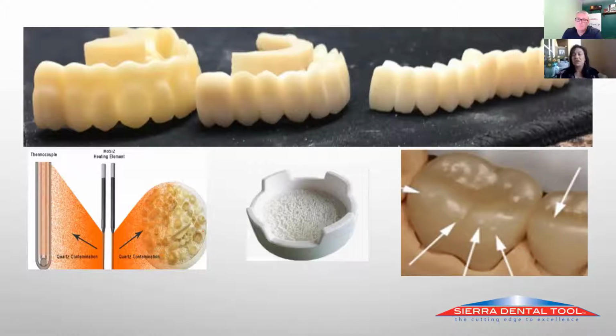Half of the solution is to change your beads, or to clean out your tray if you're not using beads, but that's sort of a band-aid. The real solution is that you need to purge your furnace, or those flakes, the quartz, are going to fall right back into the next tray, and this will continue to happen. So we want to run a purge cycle.